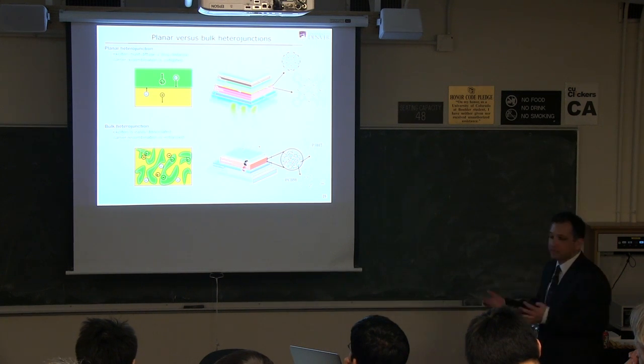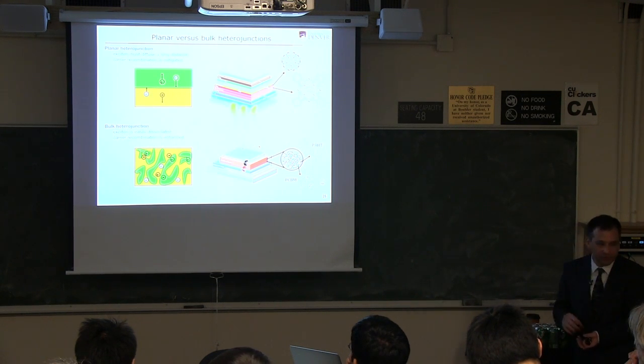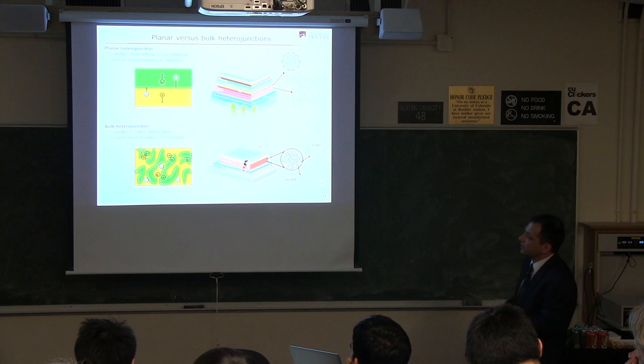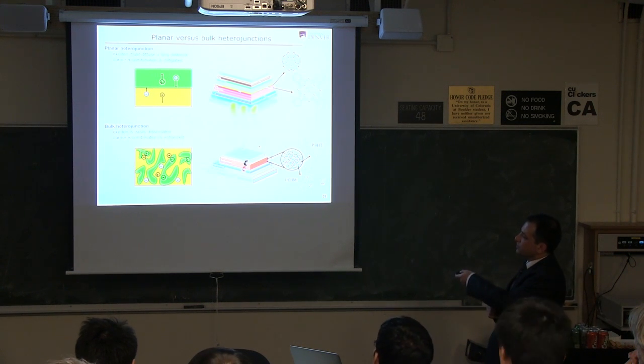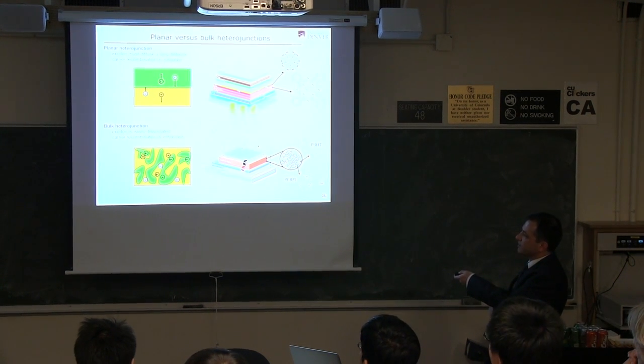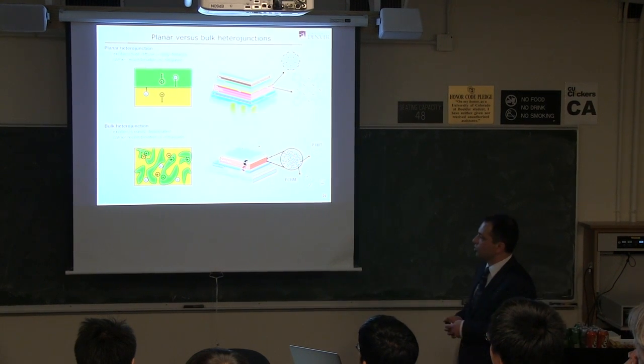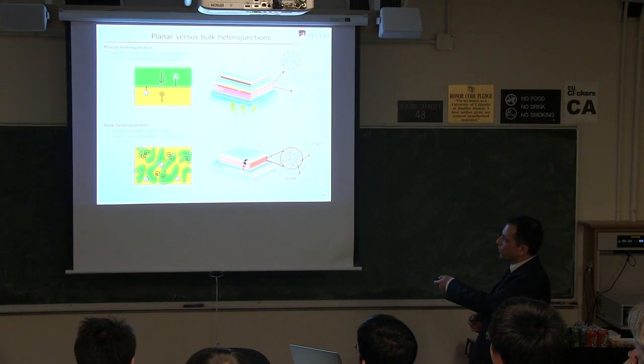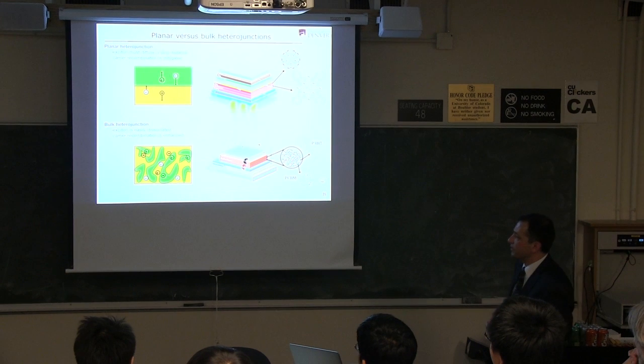The way around that is the bulk heterojunction. It's an intimate mixture of the donor and acceptors. Simply mix them in powder in the vial, pour in the solution, mix them up, and go. The advantage here is that there's close separation across the whole bulk of the film, so all the excitons, or 98%, become dissociated into charges because they can always quickly find an interface. But now you see the problem.